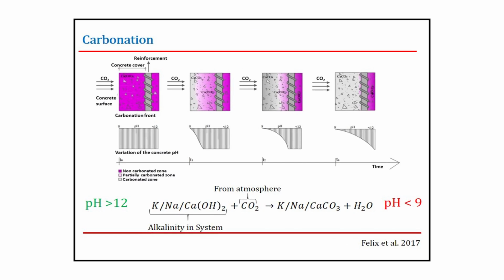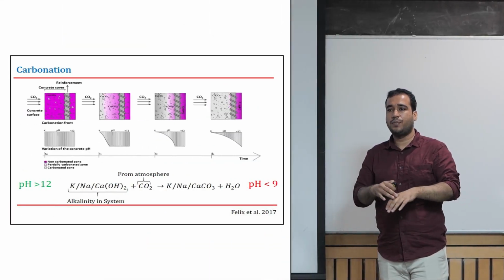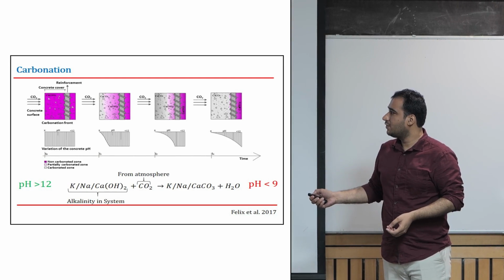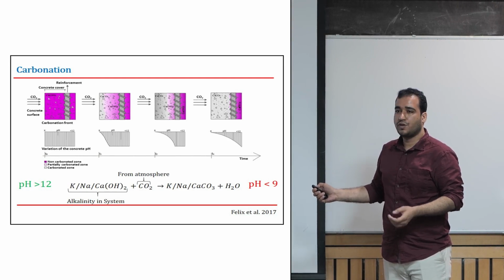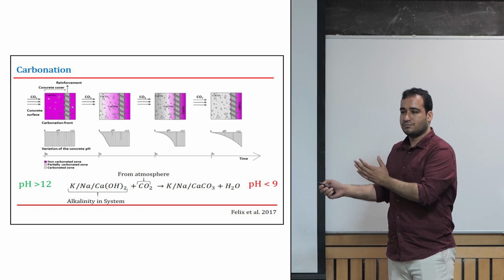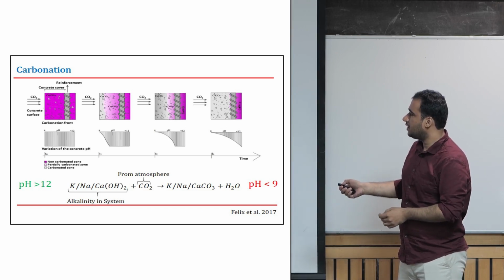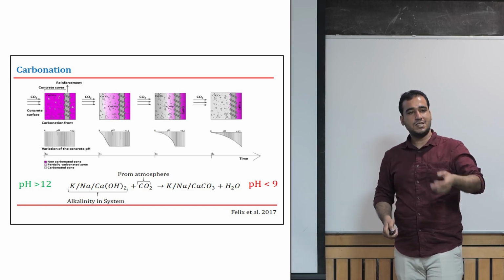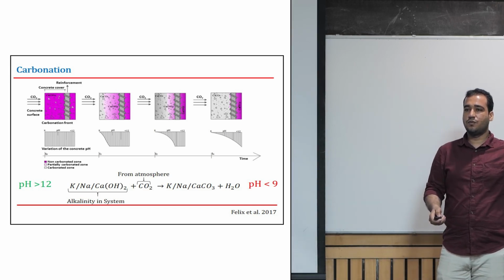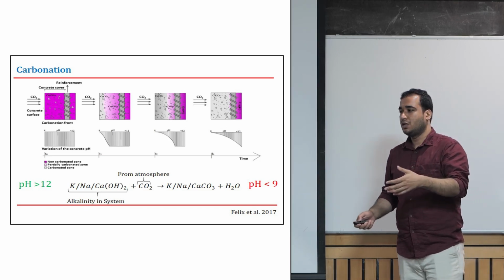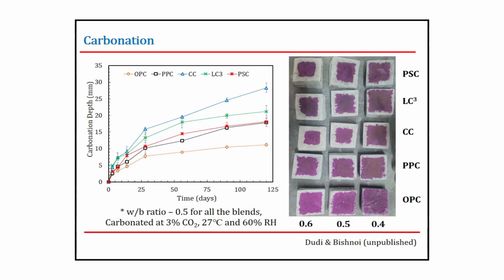The species like calcium, sodium, and potassium, which were causing your high pH, now start to go out of the system. You start to see your pH fall. This pink color shown is a phenolphthalein indicator. When you spray a phenolphthalein indicator, when pH is greater than 10, you have a bright pink color. So you see with the carbonation front moving, this pink front is moving backwards, and when it reaches the rebar, you see the pH is less than 9. Now when pH is less than 9, you have lost your passive film, which was actually protecting you from the corrosion. Now the active corrosion will start.